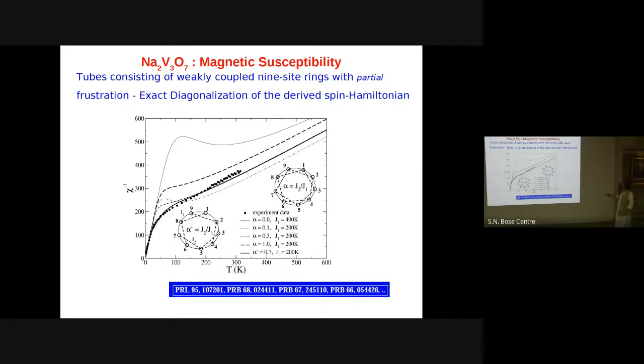And what is shown here is the exact diagonalization result of this derived spin model to get the susceptibility. The solid symbols, the circles, are the experimentally measured susceptibility, and the black line is our calculated result for the partially frustrated spin ring model. Just to check how good is our model, we consider a completely frustrated one where we put by hand all this missing dashed interaction. Also, we varied the ratio of these 2 interactions, the dashed interaction and the solid interaction, and we find actually the DFT derived model gave the best result.